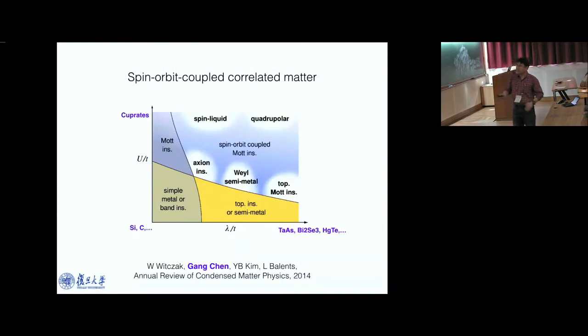So this is the very well-known schematic phase diagram of the interplay between correlation and spin-orbit coupling. This is the correlation axis, and this is the spin-orbit coupling. When there is no correlation and no strong spin-orbit coupling, the system will be a simple metal or trivial band insulator. If you turn on the correlation, you can localize the electron and form these Mott insulators. A physical example would be the famous cuprate high-temperature superconductors, the parent state of high-temperature superconductivity.